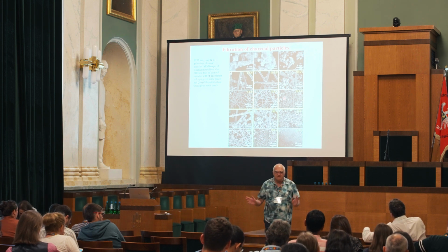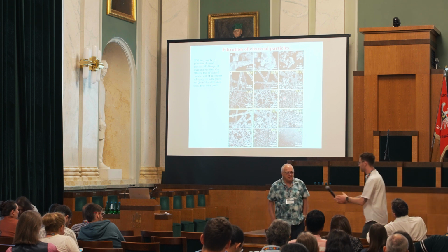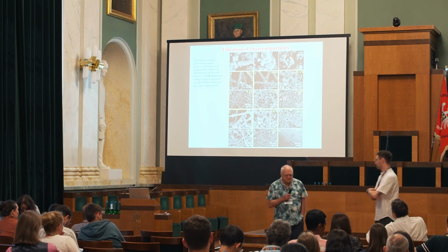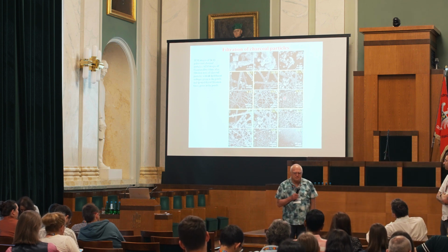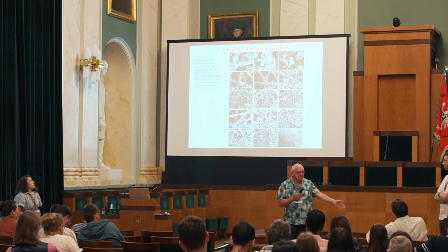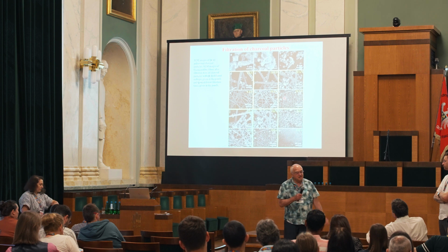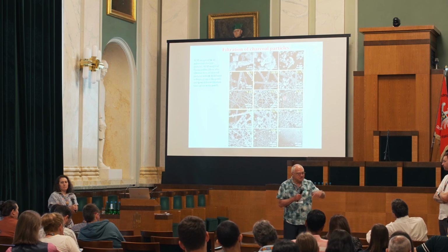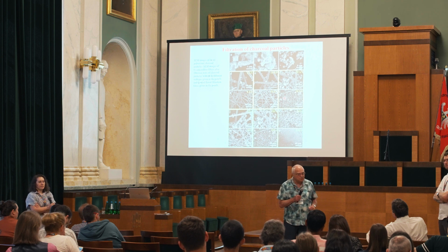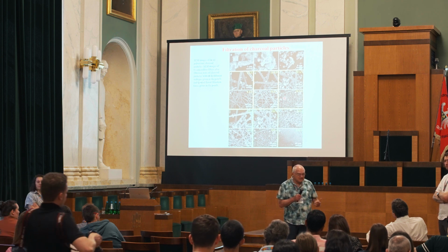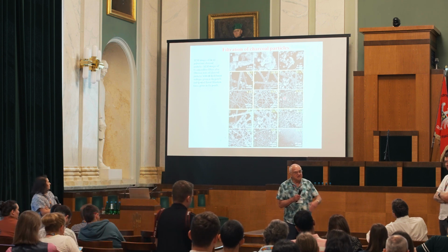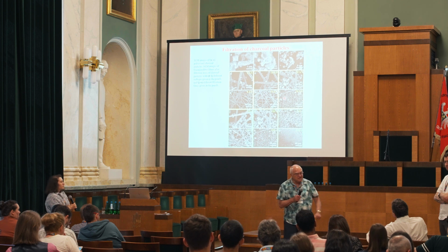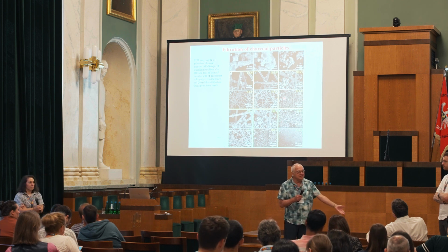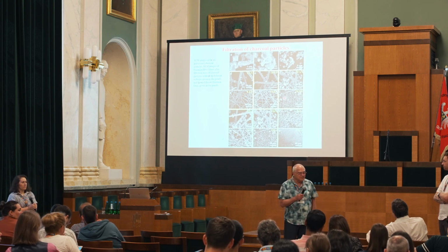Yes, we did experiments where fibers were without any metal coating. Then you measure pure van der Waals. Then you add metal coating and measure the interaction once again. Then you have van der Waals plus Coulombic forces. Then you can compare, and you see that van der Waals yields this, and Coulomb adds something else. That's how we distinguish.